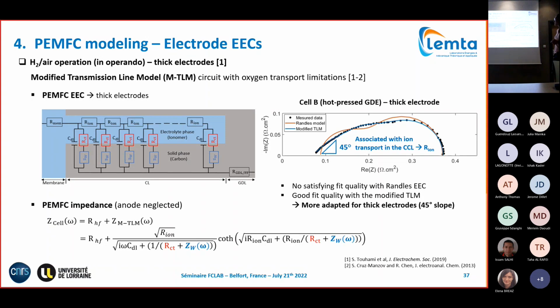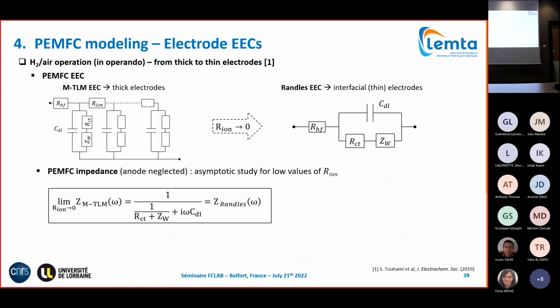ionic conduction resistance. In this case, protonic conduction. So again, here we see the expression characterized by the charge resistance and a Warburg element. And if you see here in blue, when we fit our experimental spectrum with this modified TLM, we have a satisfying fit quality. And what we analyze is that we can show mathematically that if we neglect ionic resistance, your TLM corresponds to a Randles circuit. We will obtain the same expression.